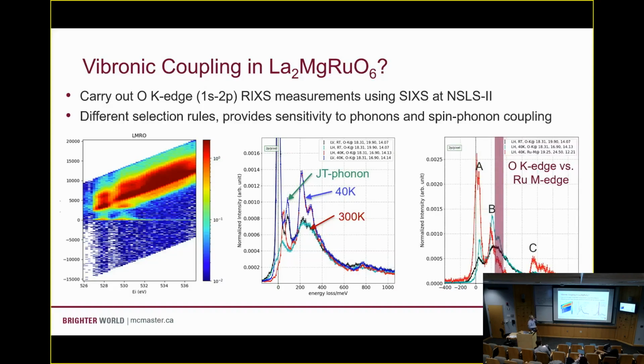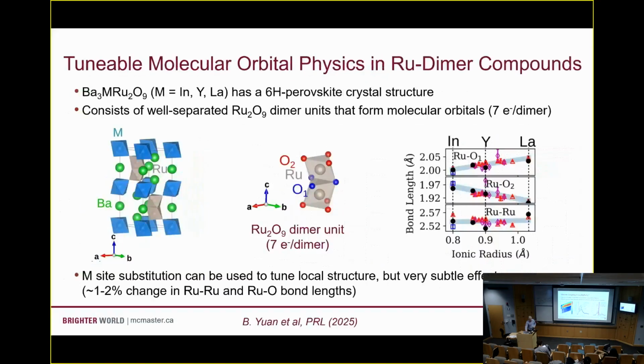Okay? So we know that the tetragonal crystal field splitting is important, but these vibronic effects also seem like they contribute as well. Okay. So maybe in the time that's left, I'm just going to tell you a little bit about this other story. So LMRO, this excitonic magnetism picture, this is all still dealing with localized ruthenium magnetism. The interesting thing about this dimer system is that this is a cluster magnet. Okay, so it's a material that's based on these ruthenium oxide dimer units.